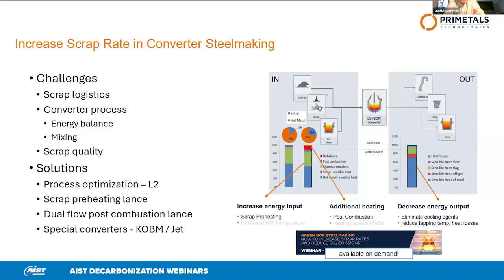To melt more scrap, we need more energy. So we have to keep this energy balanced, what we take in and what we take out. And we can work on this energy balance by bringing in additional energy, for example, by scrap preheating, by additional post-combustion, or simply by better process control to reduce energy losses, by better logistics, and by eliminating all the cooling agents that are still used today in converter steelmaking.